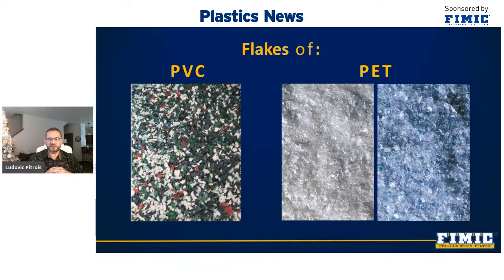Since then, we have seen a lot of interest from recycled PVC companies for our FIMIC filter, as it is the only solution to filter this type of very sensitive material continuously and not manually. Our system will check the ease and speed with which the material flows within our filter, which present no dead spot nor any corner where the material can reside and therefore degrade, which we know in PVC is often a real issue.